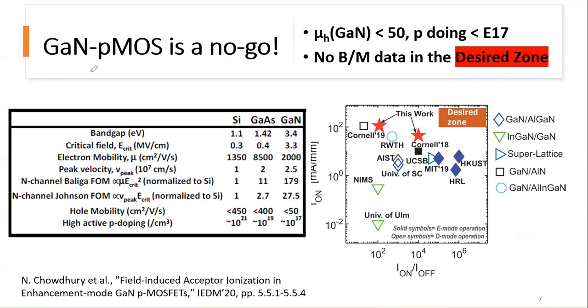How about just a PMOS, gallium nitride PMOS? This is a no-go. The reason is pretty simple. The hole mobility of gallium nitride is less than 50. You can see in the table on your left it's less than 50. The hole mobility is very poor. And doping, don't forget about the doping. It's very poor too. It's very hard to dope gallium nitride with P doping.